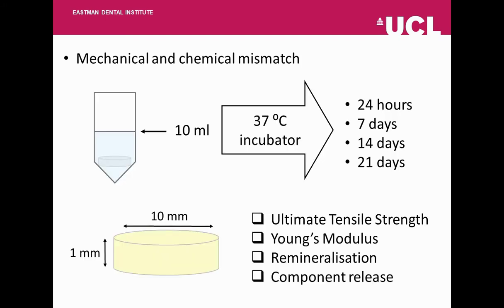So to test this assay, I prepared discs 10 millimeters in diameter and 1 millimeter in thickness. They were placed in 10 milliliters of simulated body fluid and were left to incubate for 4 different time points. Using this assay, I looked at 4 different properties. The mechanical properties, where I looked at ultimate tensile strength and Young's modulus, and to look at the chemical properties, I assessed remineralisation and component release.